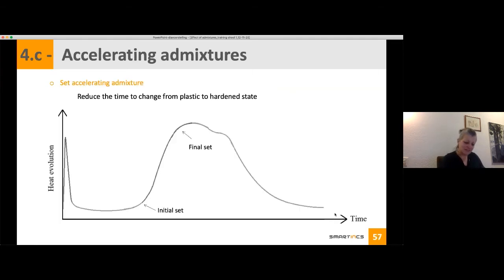Now, if we move on, like we said, retarding, now we will go to the opposite effect. If we look at accelerating admixtures, we have two types here: the set accelerating and the hardening accelerating. I will first start with set accelerating admixture. It has to do with the setting. It will reduce the time to change from plastic to hardening. So this part of the curve, when it starts, will just shift to a lower time, but you see that the rate of your hardening, between your initial and final set, the slope is the same. So it only influences the start of your initial set.